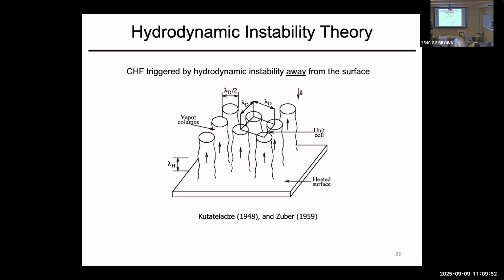So basically, the idea is that the source of critical heat flux is away from the surface, in the fluid. The gas is moving with such a velocity that the liquid pathways that are coming back, the interface between the two, becomes unstable. So then you cannot get enough liquid to come back. Really, vapor pushes the liquid on top, and then you get to the critical heat flux. So in this case, the scientists were surprised, if you look at the literature in that era, that it's purely hydrodynamic. It doesn't have to do with other factors.